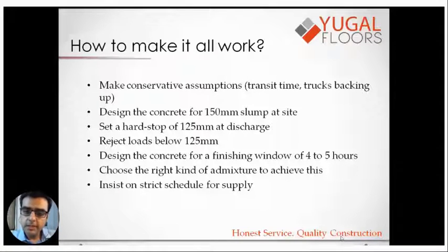Now, what this does is it gives you a cushion of about 25. So let's say for whatever reasons, delays, gaps in the trucks, your slump drops to about 125. You can still use that concrete because that is your lower end. But be sure to reject loads below 125 because the concrete guy would just dump this concrete and leave, but you're the guy who has to deal with it and finish it. The liability is yours the moment he has dumped it in the panel. So you have to be very careful about your contract with the concrete supplier.